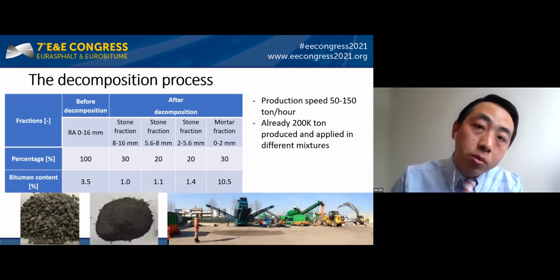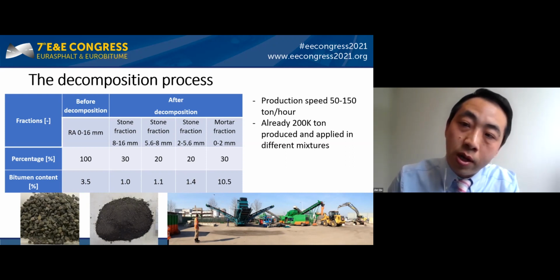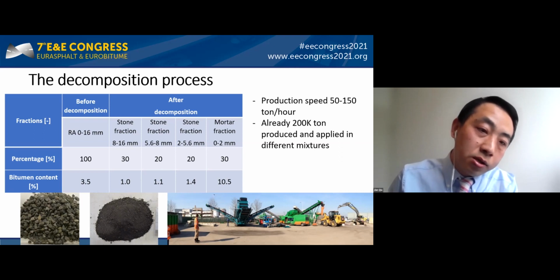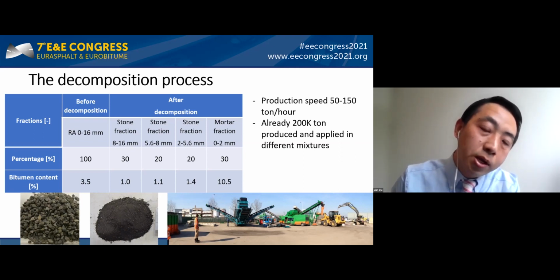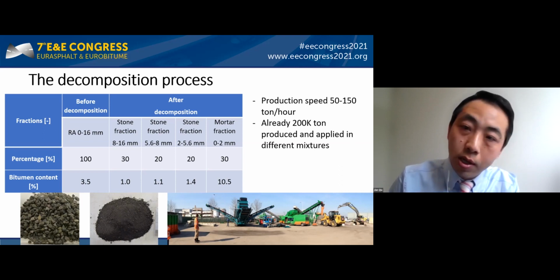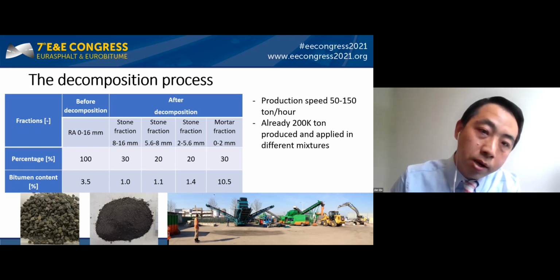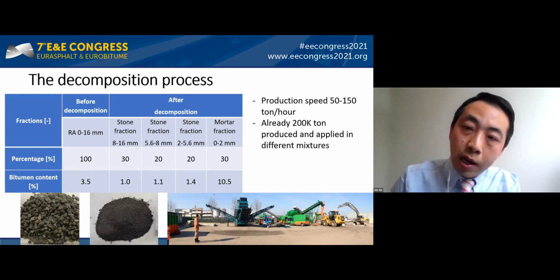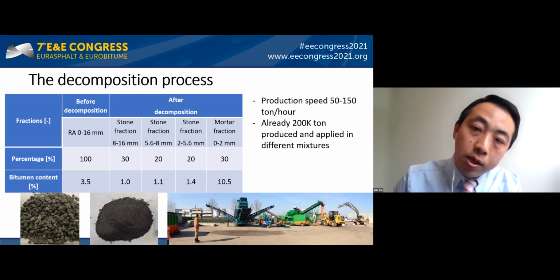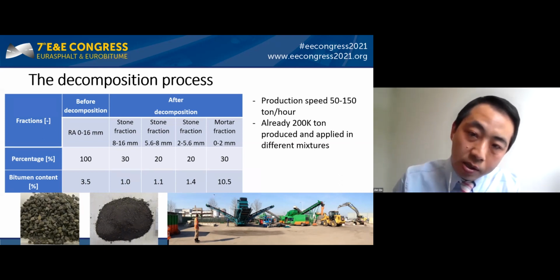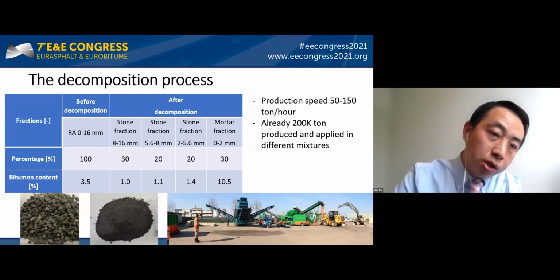A little bit about the decomposition process. It is more like a very big centrifuge machine. It runs at 50 to 150 tons per hour. Actually, what you do is throw the RAP onto a high-speed wall. With the speed, it breaks apart, and afterwards you can sieve it out into different fractions. At this moment, we have already applied 200,000 tons into different mixtures, with good experience.